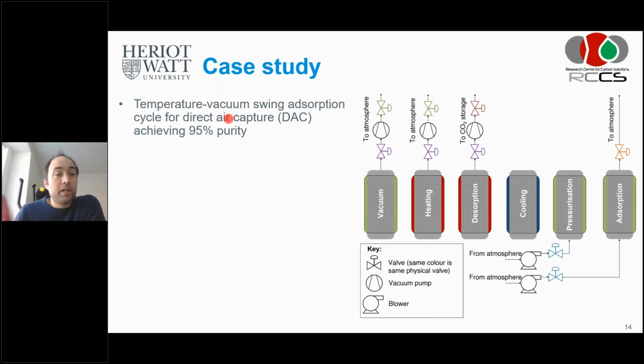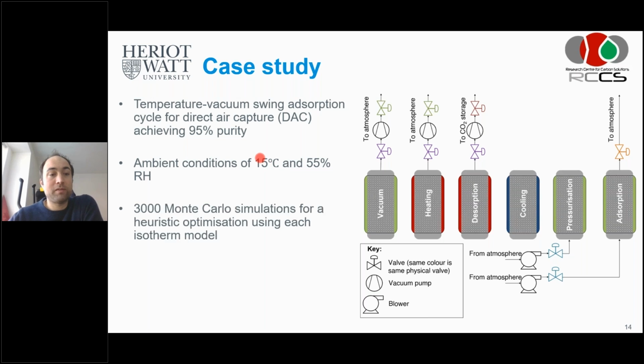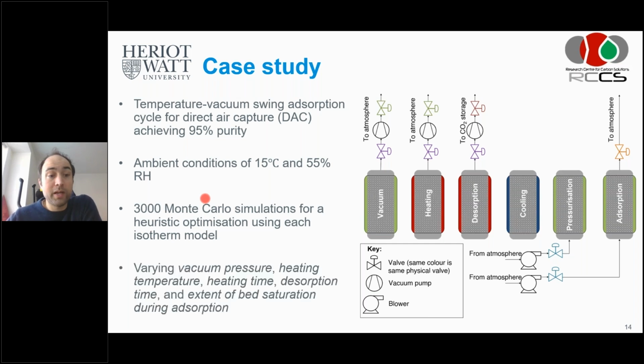It achieves over 95% purity, almost always. No, I mean not almost always, but that's the cutoff that we took. We modeled now for ambient conditions of 15 degrees C and 55% relative humidity, and we did 3,000 Monte Carlo simulations for heuristic optimization using each of the isotherm models that we had. And what we varied was vacuum pressure, heating temperature, heating time, desorption time, and the extent of bed saturation during adsorption. So instead of timing the adsorption step, we had a cutoff point for the amount of saturation, which is actually much more helpful if you're trying to optimize a cycle.